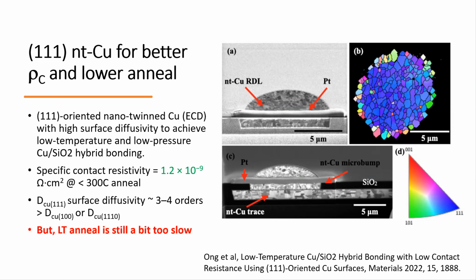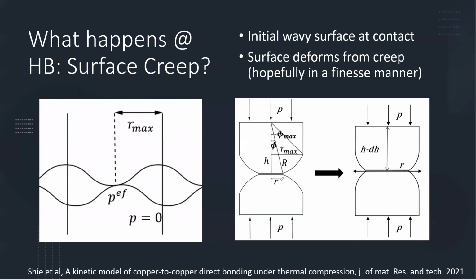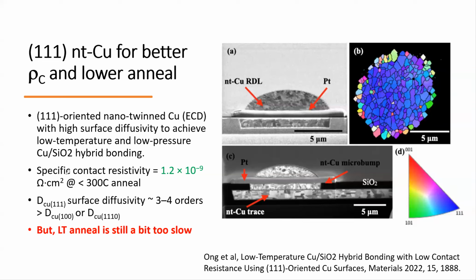Let's go back to this picture. When you touch two coppers together and squeeze them, they will start to creep. This creep is a surface creep. You don't want a bulk creep, you want a surface creep. The creep requires the surface atoms, the copper atoms, to move. That is the surface diffusivity. So the quicker it moves, the better, isn't it? So you want a specific copper that can move quickly. And 111 is claimed to have a surface diffusivity three to four orders of magnitude higher than 100 or 110. Okay, yeah, that's pretty scary. Okay, scary good.